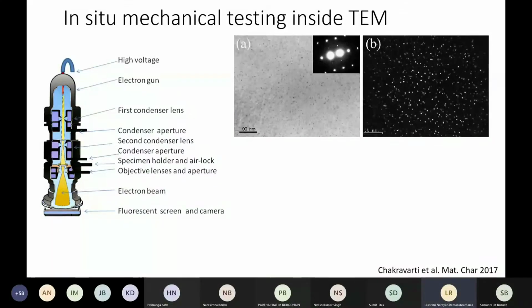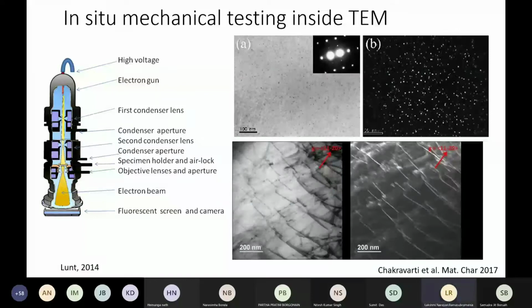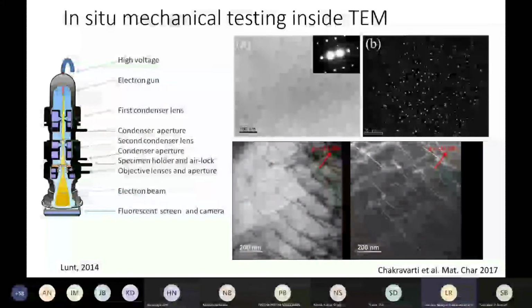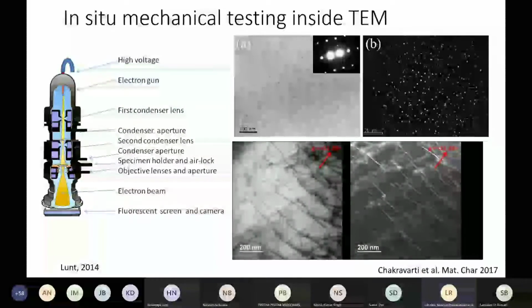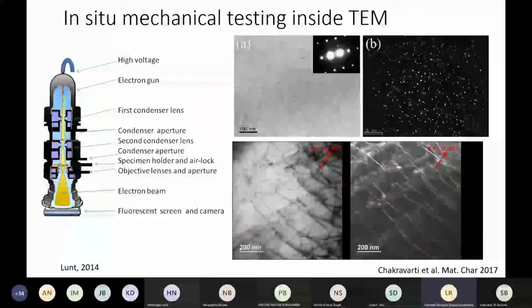And when you do imaging with one of these diffracted spots, which is shown in the inset of figure A, you will obtain an image which has a dark background but bright spots. So the imaging done by the diffracted beam is known as dark field imaging. Let's not go into details of that. What it essentially implies is that if you use one of the diffraction spots shown in the inset of A, you are going to obtain a feature that is captured by the property of that particular diffracted spot. This technique is very popular especially to determine dislocations. You can see several dislocations here, and the bright field as well as dark field images show some contrast, because the beam can also diffract through a dislocation, since it represents a mismatch in the order of the plane, or rather the arrangement in an atomic plane.